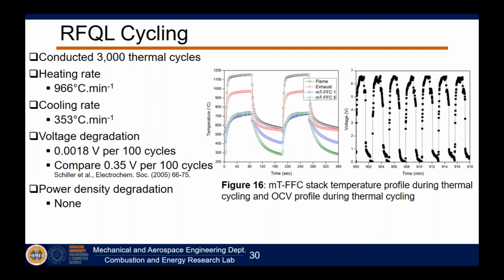So we haven't completely eliminated the seals. We used a microtubular solid oxide fuel cell, which has reduced sealing constraints. We were able to use that in this setup to achieve very high heating rates and thousands of thermal cycles. So 3,000 thermal cycles, to give you a ballpark, would be roughly equivalent to a heating season if you have an old furnace. Some newer furnaces could be much less potentially. It depends on the thermal mass in your building.